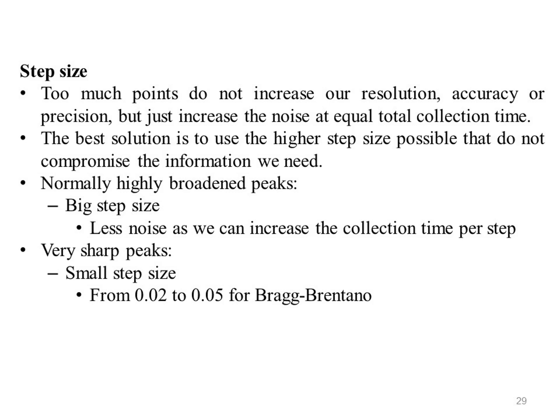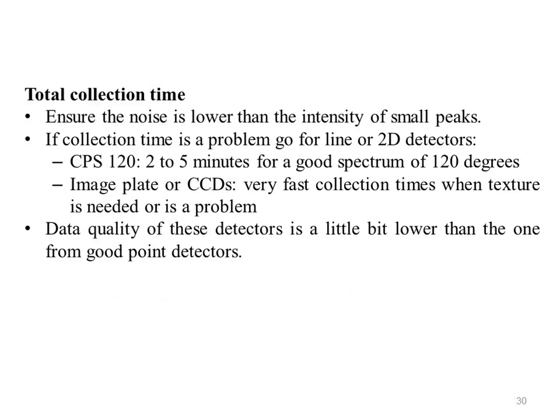The best solution is to use the highest step size possible that does not compromise the information we need. Normally, for highly broadened peaks, use a big step size, less noise, as we can increase the collection time per step. For very sharp peaks, use a small step size, from 0.02 to 0.05 for Bragg-Brentano. Total collection time should ensure the noise is lower than the intensity of small peaks. If the total collection time is limited, better a lower noise than a smaller step size. Better to collect a little bit more than to have to repeat an experiment. If collection time is a problem, go for line or 2D detectors.